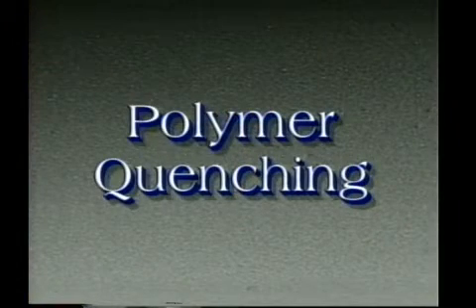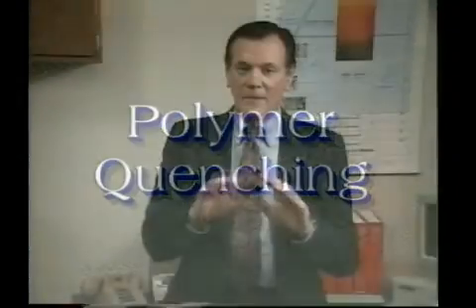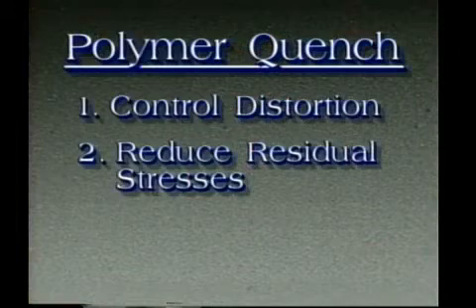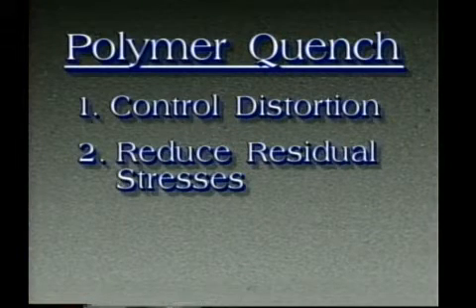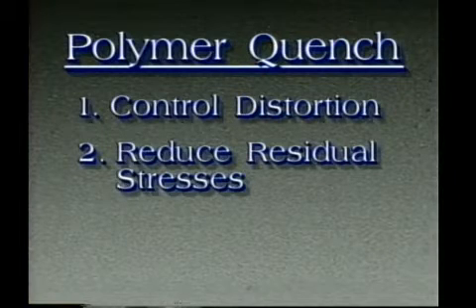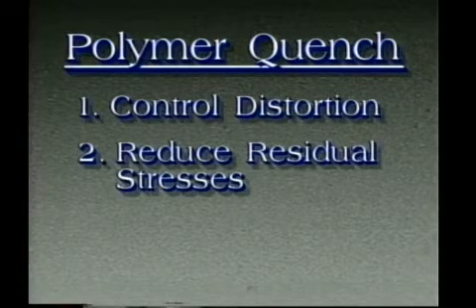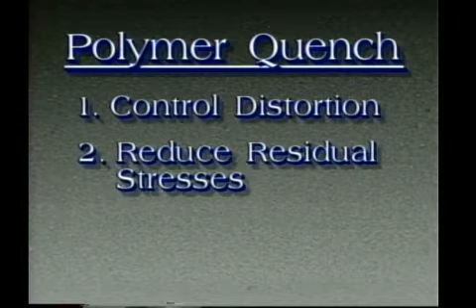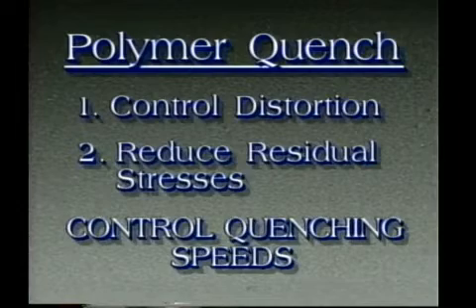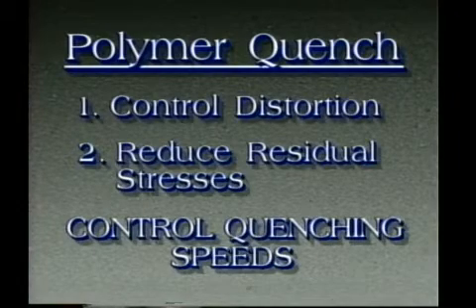Applications of polymer quenching techniques to aluminum alloy heat treatment has allowed the heat treater to achieve more consistent results when attempting to solve quenching-related problems. The two main advantages of using polymer quenchants are, one, the control of distortion, particularly in thin sheet metal products, and two, the reduction of residual stresses in the quenching of larger parts, such as forgings and castings. The polymers allow for precise control over quenching speeds, which is not achievable through the use of hot water. Polymer quenchants have found wide application for most aluminum products, such as sheet material, extrusions, forgings, castings, and especially fabricated parts which have been machined and/or formed.